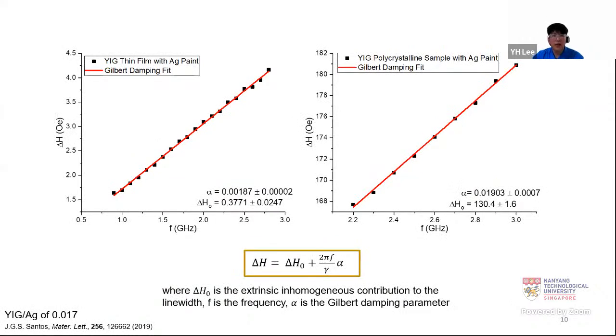We moved on to look at the Gilbert damping parameters of both samples. On the left-hand side is the thin film covered with silver paint. We see that alpha is actually very small, about 1 times 10 to the power minus 3. However, the bulk sample is slightly bigger, but as we were preparing this report,